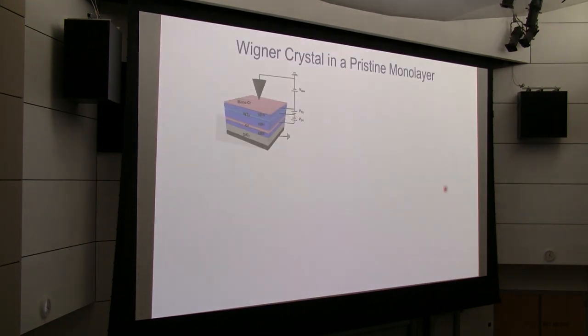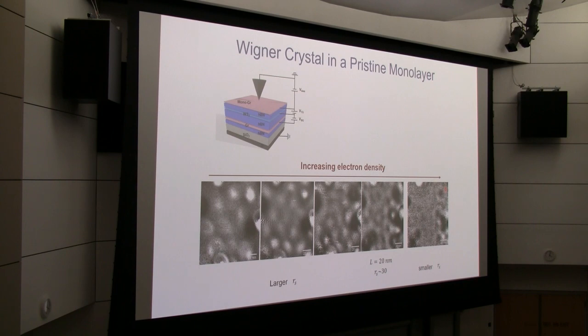Let's say we build a heterostructure, swap out the Moire superlattice, and just put in a monolayer transition metal dichalcogenide. In this case, we'll have a real 2D electron gas sitting in the monolayer TMD, and we can see whether a Wigner crystal will indeed emerge at low density. So this is a recent picture of electrons that we can see. On the left-hand side is when the electron density is very low. You can see there's roughly a lattice over there.